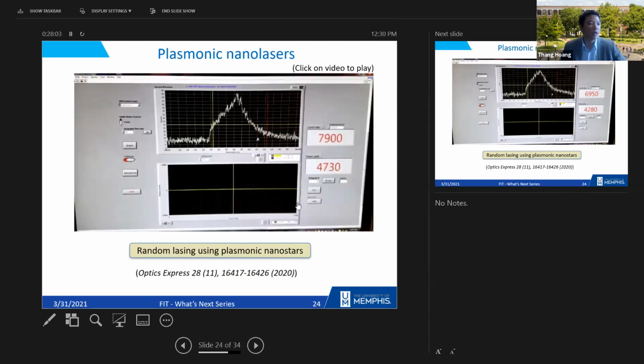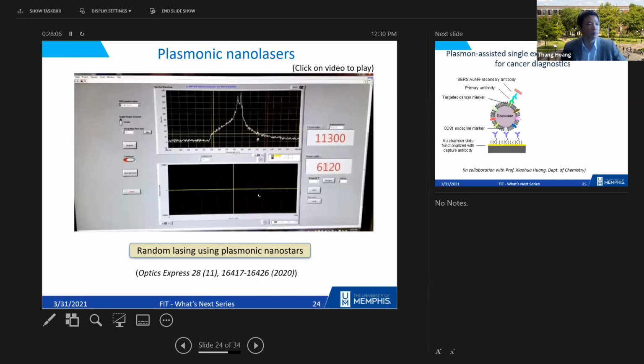And here I want to show an example of the lasing from the nanostar that is coated on an optical fiber. You see that. Here are the emission spectra, taken at different excitation power. At low excitation power, it shows very broad emission, but when the excitation goes up, it shows a very narrow peak, which indicates lasing behavior. And we can basically demonstrate it in real time, actually. So it's really a working device.